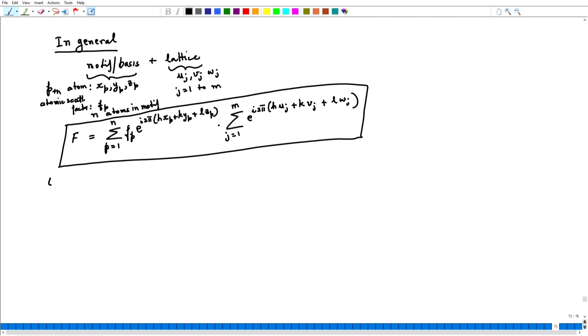Let us say I am now going to take example 2, and this example is of a NaCl crystal, which is again face centered cubic plus a motif, let us say chlorine ion at 0 0 0 and sodium ion at half half half. Now, I want to calculate the structure factor for this. So, chlorine ions are at the corners and face centers, and sodium ions are at the body centered position and also at the center of all the edges.